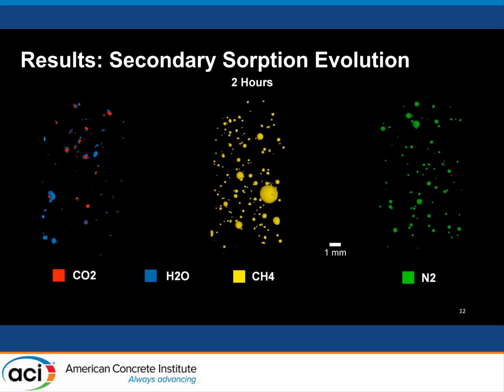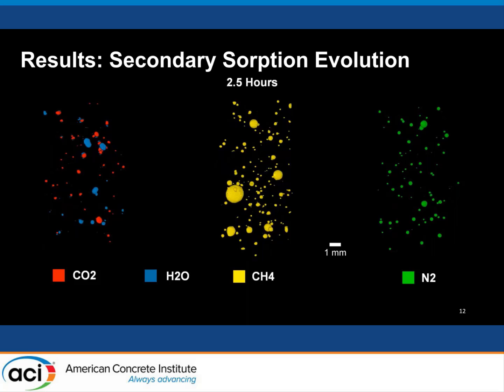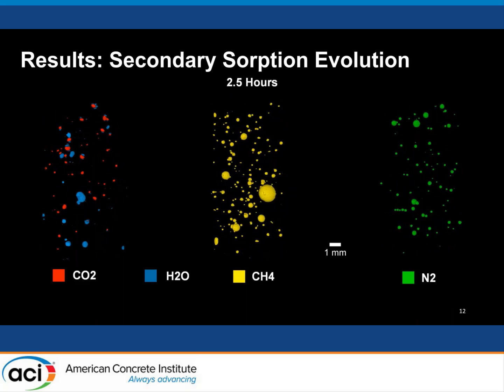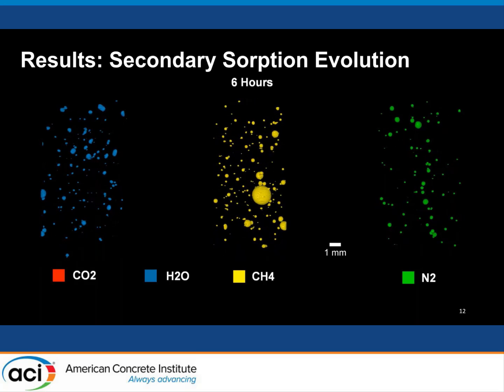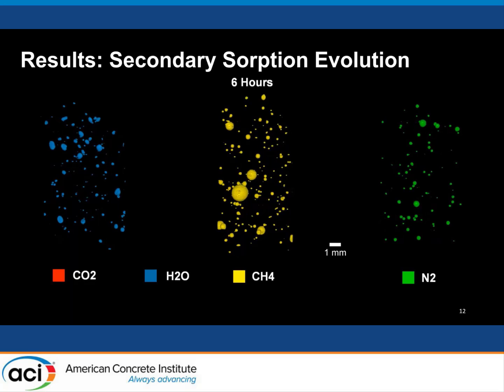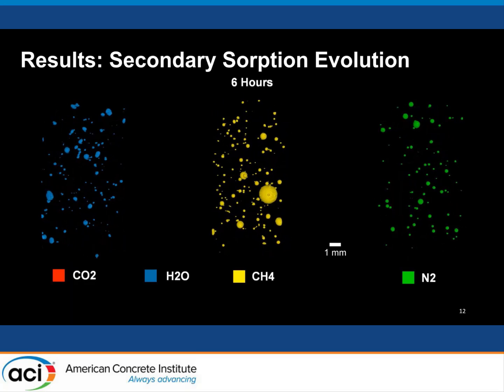And even at 2 hours, we're still not seeing any advancement in the methane or the nitrogen sample relative to the CO2 filled voids. And then we eventually reach even 6 hours, and the CO2 filled voids have actually become completely saturated with water and still no change with methane or nitrogen.